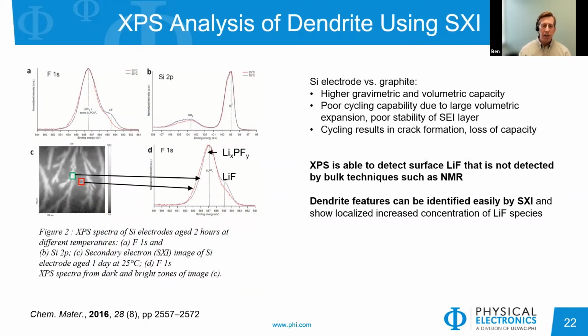And so with XPS, what we're looking at is the spectrum from 2 different regions, and this is an SXI image that was collected on a VersaProbe. An SXI is a scanning X-ray image. One of the advantages of the PHI instruments is that we scan our X-ray beam, and so we can collect an image from the sample by scanning the X-ray beam and then collecting secondary electron images, similar to an SEM. And what we see here are areas of bright and dark, and that's related to a secondary electron contrast between different regions.